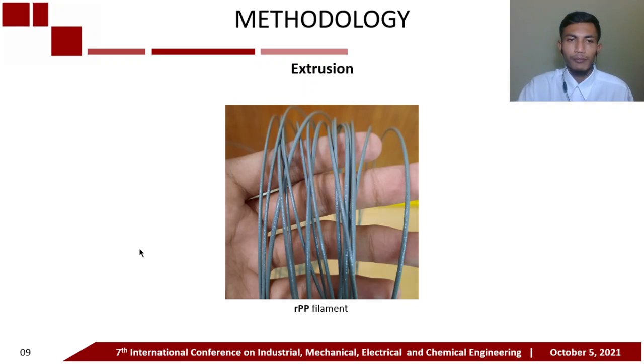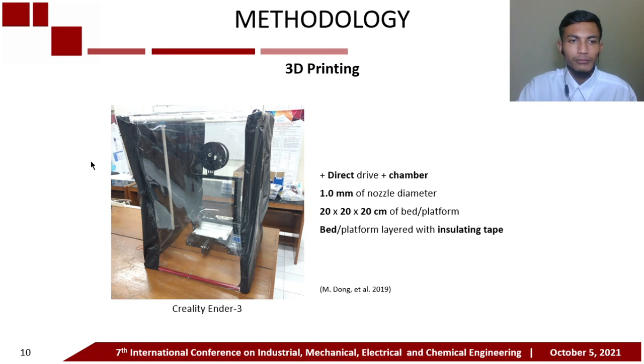Then the filaments are processed in 3D printing. The 3D printer machine used is the Creality Ender 3 with several modifications. There were the replacement of the main drive with a direct drive, and the use of a chamber to maintain the ambient temperature around the machine. The last was a clear insulating tape on the bed for the printing process of RPP and PP filaments.